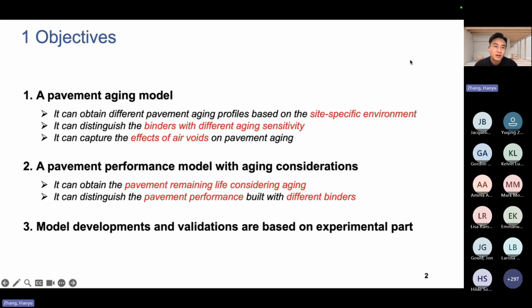I think as mentioned in Hild's part, we've already had a lot of observations on the field aging, and we realized that aging has a substantial effect on the asphalt materials, the binder properties, and also the pavement performance. So what if we can have an aging model that can duplicate the field observations? That would be a powerful tool for us to test different binders, different materials. So one of the objectives here is to develop a pavement aging model. And this model needs to obtain the different pavement aging profiles based on the on-site specific environment. It can also distinguish the binders with different aging sensitivity, and it also needs to capture the effects of air voids on pavement aging, because we all know aging is highly related to the air voids.